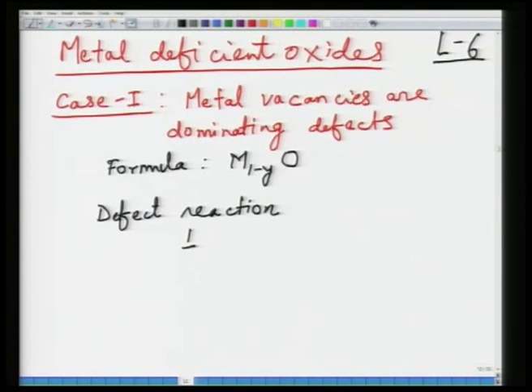The defect reaction would be, since it is a case of metal deficiency, that you have oxygen coming in, and oxygen goes to an oxygen site. We are taking the case of MO type, which means you have to maintain the site balance. So you create one oxygen site where the oxygen goes, and complementing that you have a metal site, but since this is a metal deficient oxide, you will have a vacancy of metal. Now, this vacancy of metal, since it is an MO form, would be doubly negatively charged.